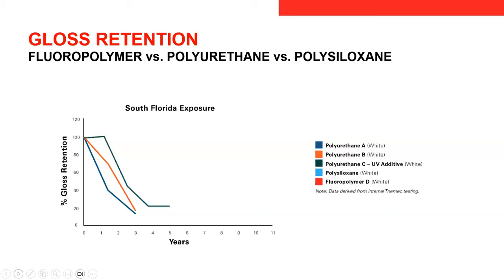So here's a third polyurethane. It holds on maybe a little bit longer, but still crashes relatively quickly within 5 years of exposure in South Florida. A polysiloxane has held on and is really looking good over that five-year period, and starts losing its gloss retention after that. And then a fluoropolymer, which is out to 9 years, and actually we have 10-year data on this, has held steady. So you're seeing a much more consistent look for the finished structure over that time, even in South Florida, which is very aggressive.